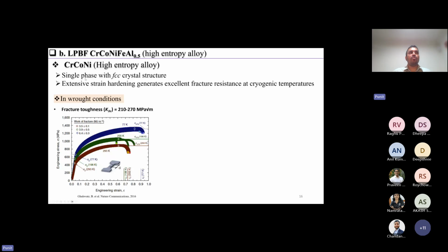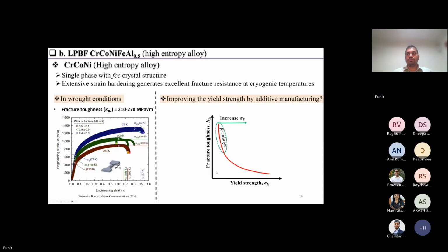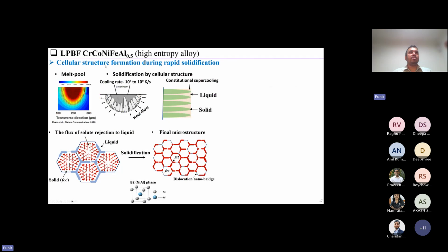So there is no incentive to actually go and use this material, which has such a high amount of cobalt, which is an expensive element, if you know about that. So the idea was, can we use additive manufacturing to increase the strength of this material without affecting the fracture resistance? So this is where we selected this composition, where we have additionally added iron and aluminum.